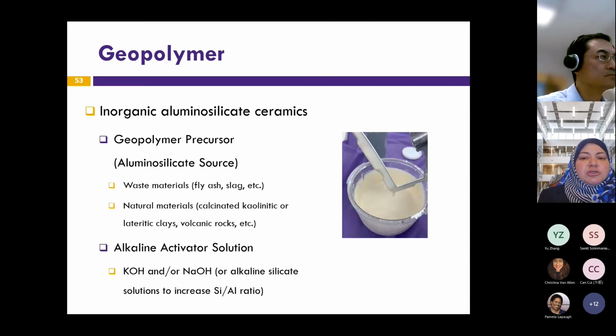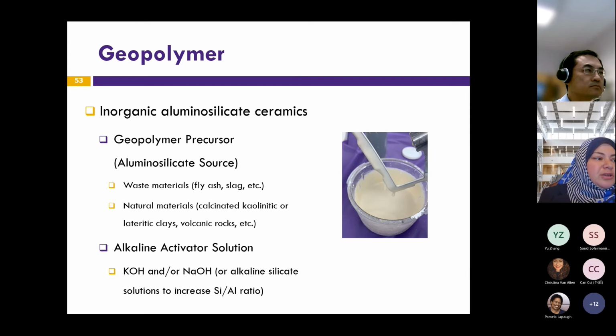Okay, so what is a geopolymer? As you all know, geopolymers are made by mixing what we call geopolymer precursor with an activator solution. Geopolymer precursors can be many things, from waste materials like fly ash and slag to naturally occurring materials like kaolinite, like metakaolin, etc. The activator solutions are sodium hydroxide or potassium hydroxide. It's an alkaline silicate solution that can increase the silica aluminum ratio.